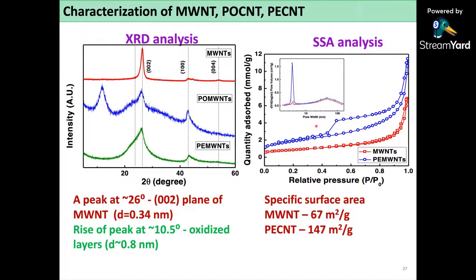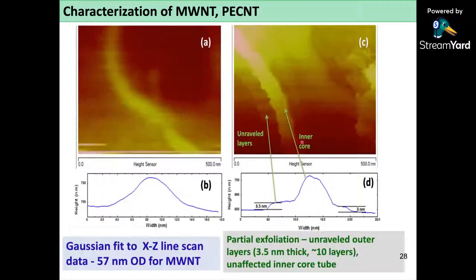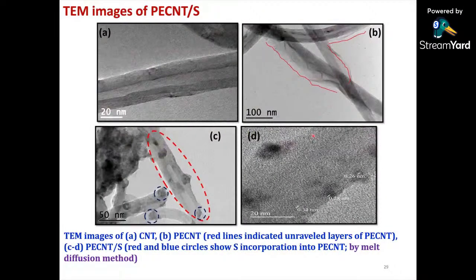But still, the inner layers are intact, therefore you have got excellent electrical conductivity, and the exfoliated layers as well as the inner core can be easily seen from these images. Then using melt diffusion, it is possible for us to use the PECNT and incorporate 70 to 80% of the sulfur. You can see the incorporation by a very simple technique.